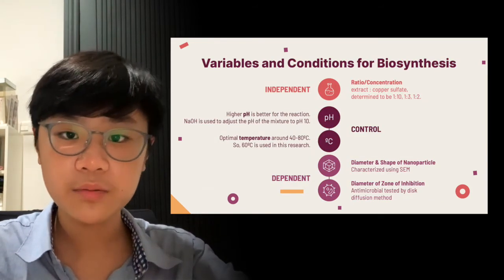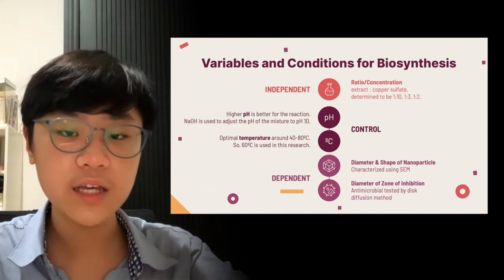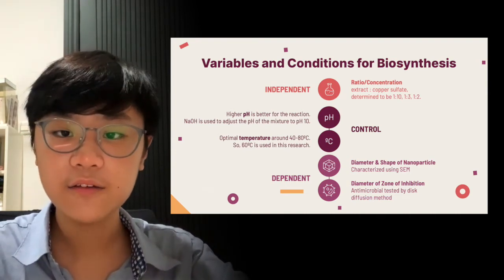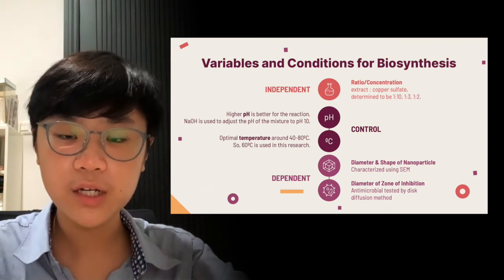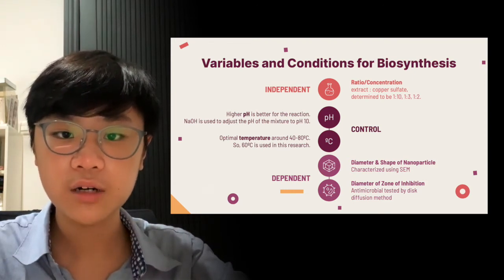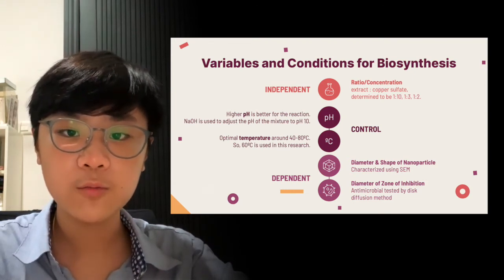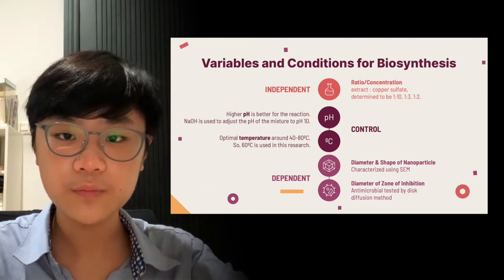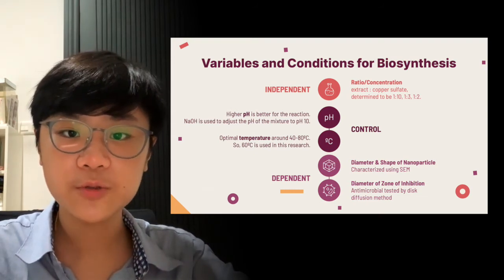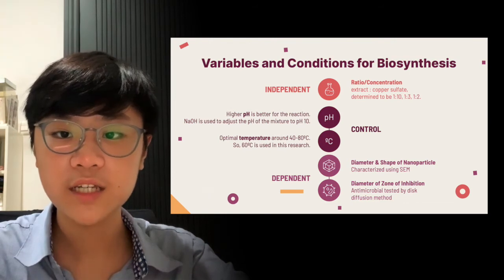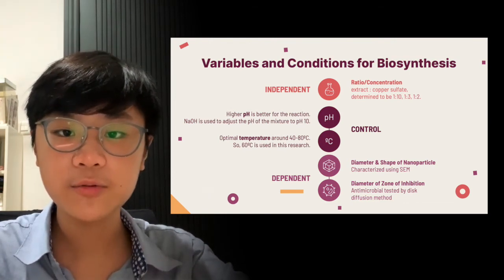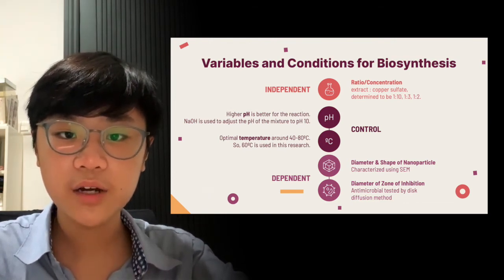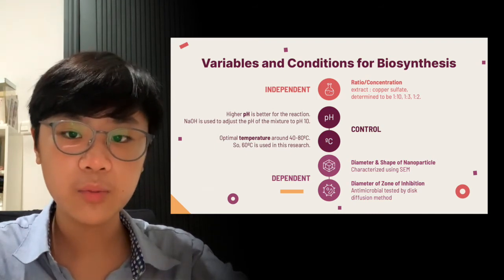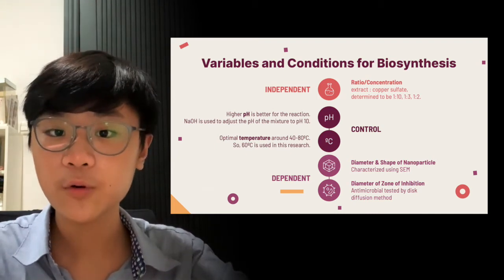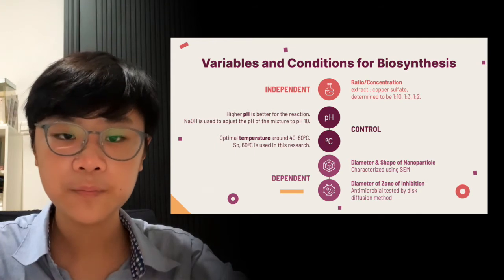For the biosynthesis process, there are specific variables and conditions that have been set. First, the independent variable is the ratio and concentration of extract to copper sulfate, which is 1/10, 1/3, and 1/2. For the control, pH was adjusted to 10 using sodium hydroxide, and the temperature was around 60 degrees Celsius. The dependent variables are the diameter and shape of the nanoparticles and the zone of inhibition for the antimicrobial test.